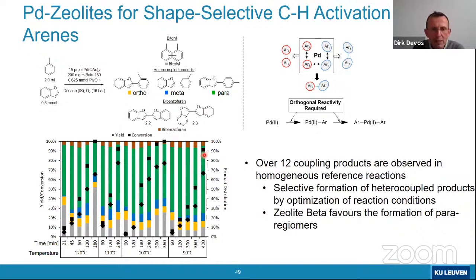But you also see that we have a significant control over the selectivity, because in brown in the graph, we show the bibenzofurans, and they are negligible. In gray, we show the bitolyls. They are also negligible, just below 10%. That means the selectivity for the tolylated benzofurans is 85%. And within that fraction, we again have a strong preference for the para-tolyl product. So even in this challenging C-H/C-H coupling of 2 different molecules, we are capable of getting high yields and high selectivities, again, in this zeolite beta environment, now appropriately adapted.